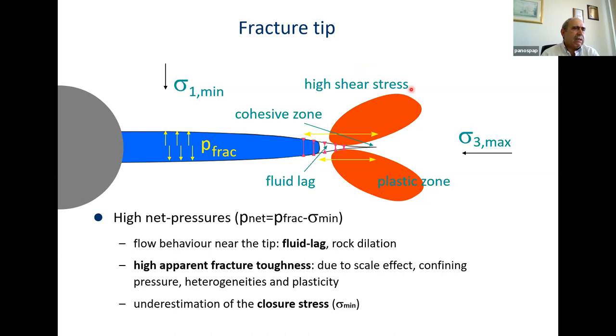And if these plastic zones are formed, then the energy will dissipate there, and not enough energy will reach the tip to split the rock. So there we will need higher pressure back at the wellbore. One can also think of it like this: the shape of these plastic zones around the tip actually shields the tip. Therefore, we need higher pressure to propagate the fractures.